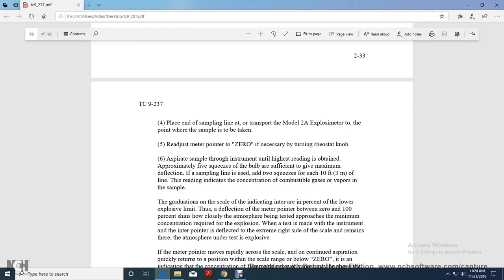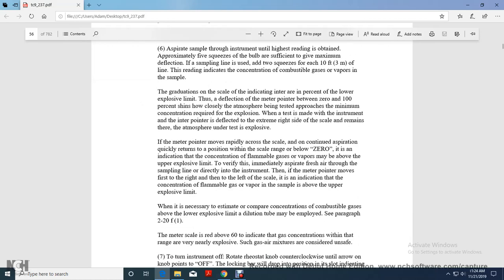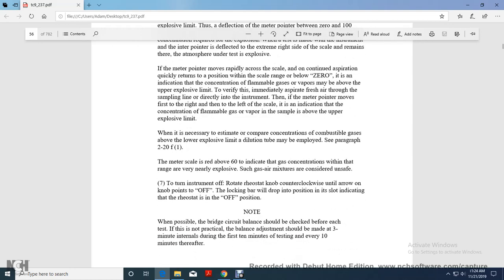Aspirate the sample through the instrument. The highest reading is obtained with approximately 5 squeezes of the bulb, an amount sufficient to give the maximum deflection. If the sample is drawn through a sampling line, use 2 additional squeezes for each 10 feet of line. The reading indicates the concentration of combustible gases and vapors in the sample. When the graduations of the scale indicate percent of the lower explosive limit, deflection of the meter pointer between 0 and 100% shows the atmosphere being tested is approaching the minimum concentration required for an explosion. When tested with the instrument and the pointer deflects to the extreme right side of the scale, the atmosphere under test is explosive.